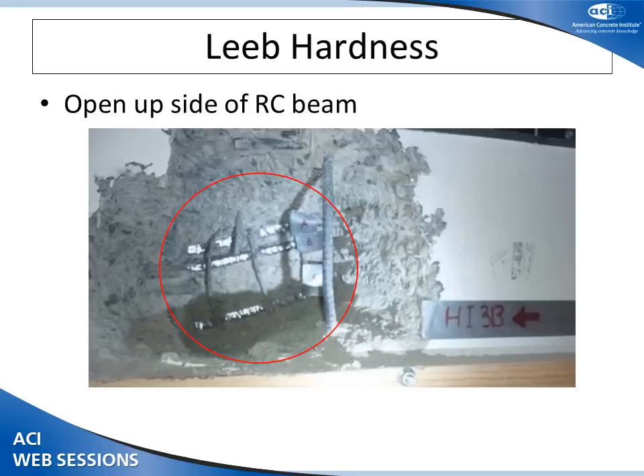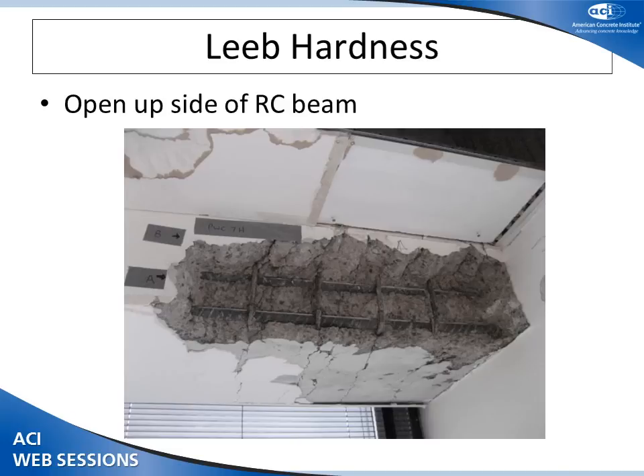Okay, just some shots. What the technicians do is they take the cover concrete off, they prepare the surface of the bars we're interested in to do the Leeb Hardness test, which is a bouncing steel ball. The change in velocity on the rebound is an indication of what the hardness is. The technicians are very careful not to use heat because that changes the metallurgy. They do the preparation with light sandpaper. That's just another shot in a plastic hinge in the Price Waterhouse building, one of our second tallest concrete buildings in Christchurch. That's about to be demolished.